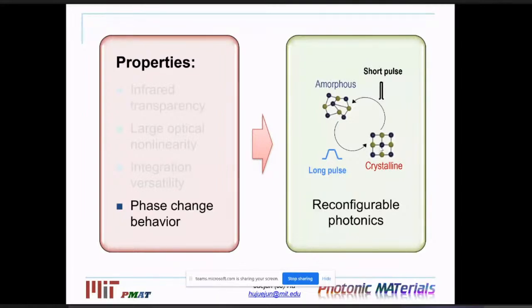So to switch from crystalline state to amorphous state, you send a large pulse with large amplitude, but very short duration. By doing so, you elevate the material to above the melting point, and then you quickly quench it down so that you can essentially preserve this liquid-like amorphous state. Now, if you want to go in the reverse direction, you send in an energy pulse that's long in duration, but smaller in amplitude. This will raise the temperature of the material to above the crystallization point, but below the melting point, so that all the atoms have enough kinetic energy to move around and find the thermodynamically stable structured state, which is the crystalline state. So this is a reversible switching material.